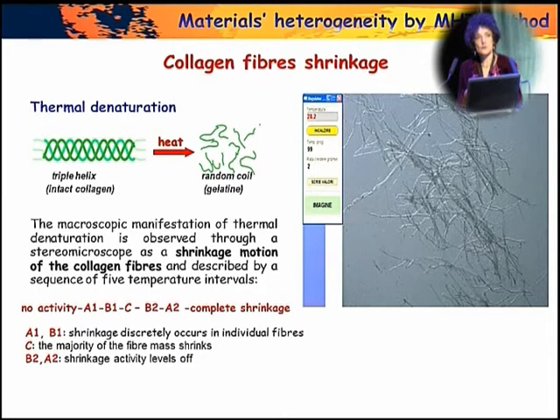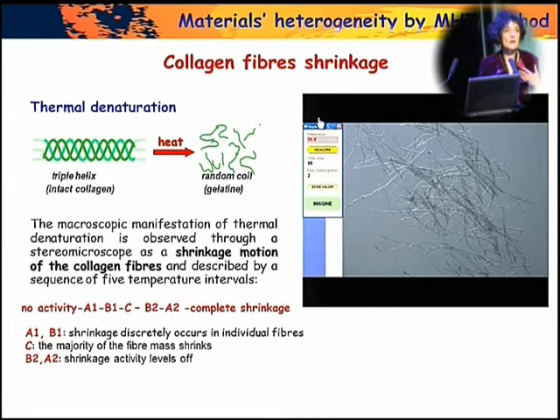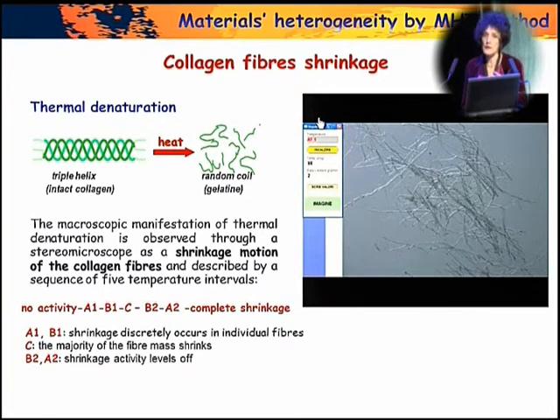People used to study parchment and leather know that probably the most widely used method for characterizing parchment and leather is the micro hot table method. Generally, with this technique, shrinkage temperature is measured. Shrinkage is the macroscopic manifestation of molecular denaturation. Shrinkage, in few words, is the motion of the collagen fibers subjected to heating under constant rate.